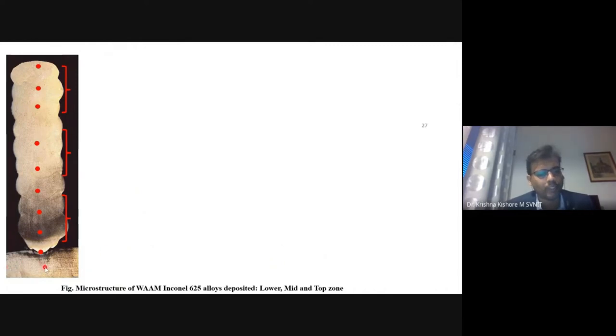So it is one complete deposition, let's say. For easy analysis, we have divided the entire height of this structure into three zones, like top, middle and bottom. And at different regions, we have considered different layers. Actually, the dots represent one layer number. So layer number one, layer number two, something like that. We have divided into an equal number of layers, and these layers are selected in such a way that we can assess the growth from layer one, let's say layer three to layer nine and layer 27, like that.